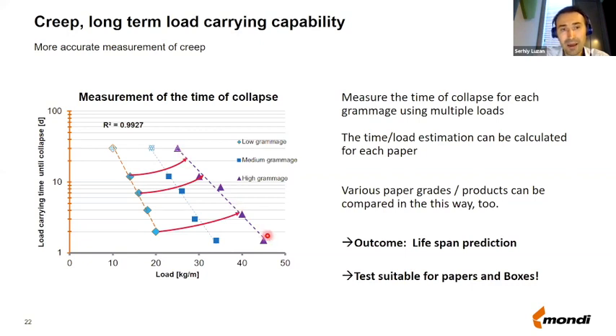And why is this information helpful? Again, as I was saying before, if you, for instance, have different paper grammages, and you know that you need to hold 20 kilograms per meter of material, then you can say, okay, so this paper will hold it for 2 days, but if I go to higher grammage, then maybe this higher grammage will hold this load for 30 days. And therefore, depending on how long you would like the paper to hold the load, you understand what kind of grammage of paper you will need. So you can predict the lifetime of your paper, and also as a result, the lifetime of the packaging.